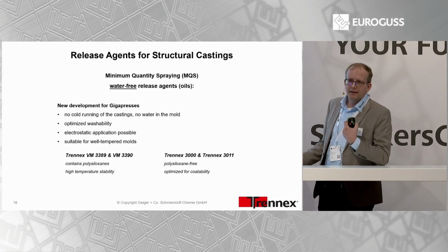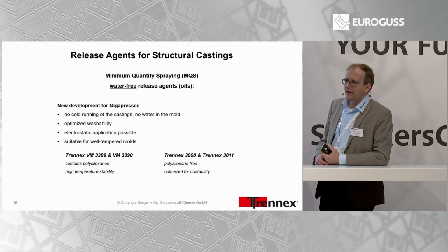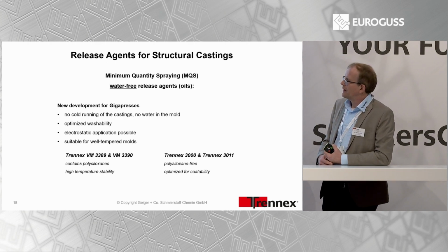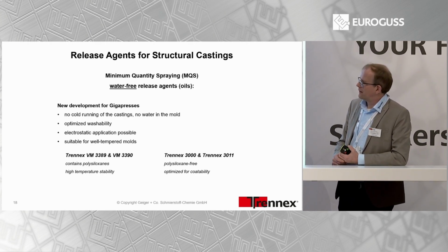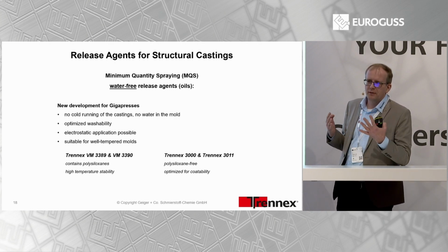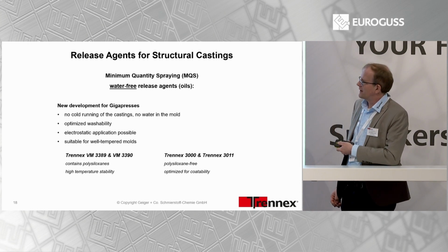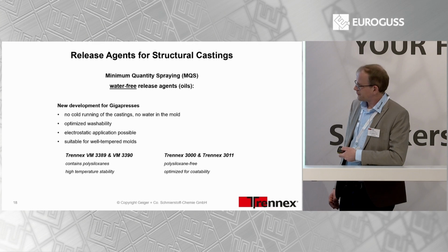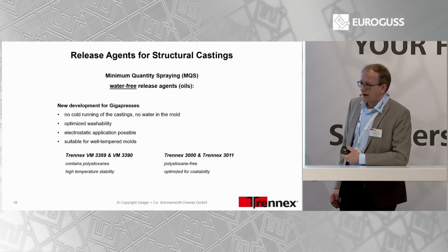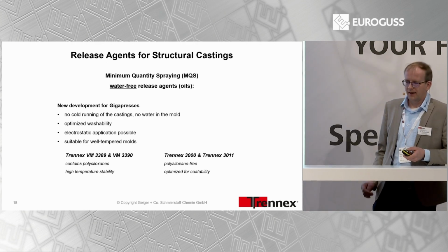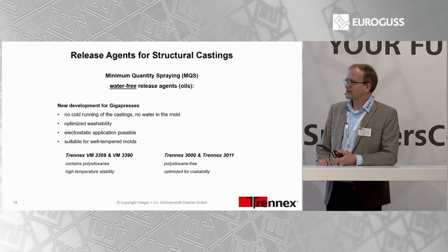You can apply them electrostatically, so we can modify them in order to make them applicable electrostatically, and for well-tempered molds where you don't have temperature problems with too high temperatures, we could say they are well suitable. And here we have, for example, polysiloxane-based products and also polysiloxane-free products, which are also quite successful for these structural castings.